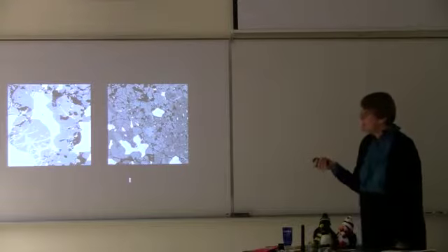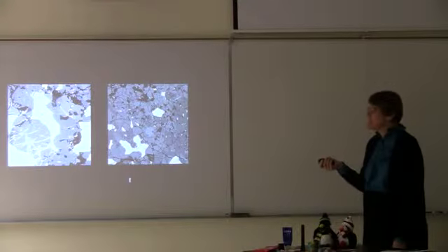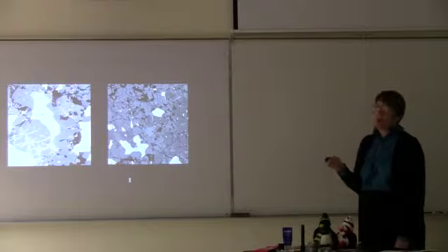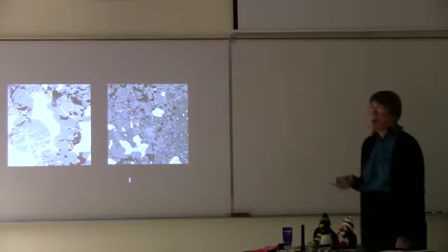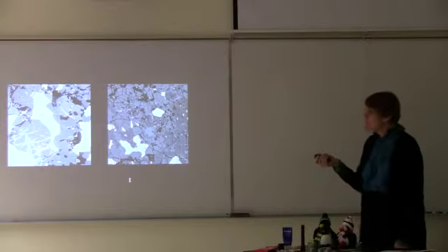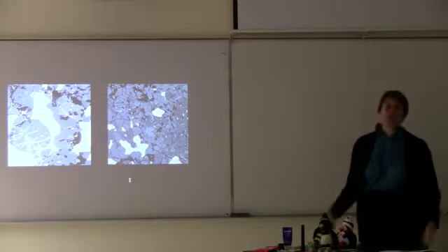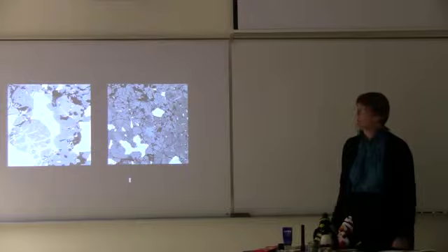And when Guy would do some calculations and estimate the amount of weathering based on their Mossbauer techniques, he could get an estimate of how much of the porosity was filled. All I had to do was look at it, measure dark cracks and measure light cracks, and I was getting numbers that corresponded to what he was calculating.